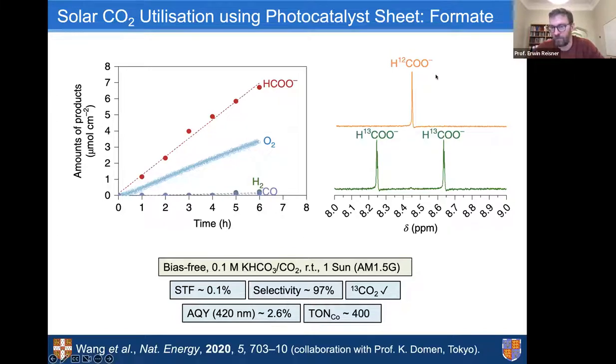We can see here from the C12 CO2 that we only form C12 formate with a singlet, because the proton is now connected to a spin 0 carbon. If we label the carbon dioxide with C13, we form indeed the C13 labeled product. And now we see this nice doublet being formed here. And this doublet is formed because the labeled C13 has spin half and forms a doublet with the proton that's also spin half in the system.